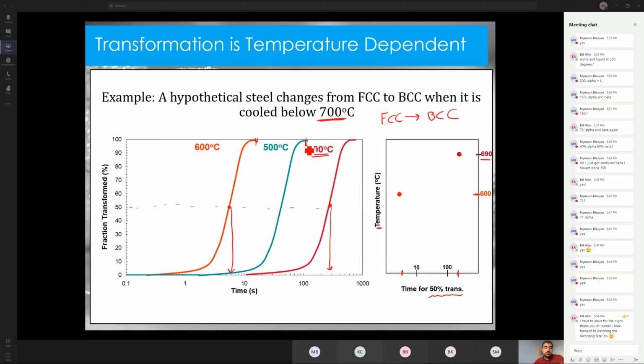The reason it's different is that there is a lot of atomic movement needed for the FCC atoms to rearrange into BCC atoms, right? They have to move around within the solid. And atomic movement in the solid is difficult. It's not like atomic movement in the liquid, right? So we call this diffusion. Diffusion in the solids is slow. It requires activation energy. It requires heat for those atoms to be able to break their bonds, move, and make new bonds. And what seems to happen in my example here is when I went to 500 degrees, even though there is a huge driving force, there is a big incentive for FCC to change into BCC, because we're at such a low temperature compared to where FCC should exist.